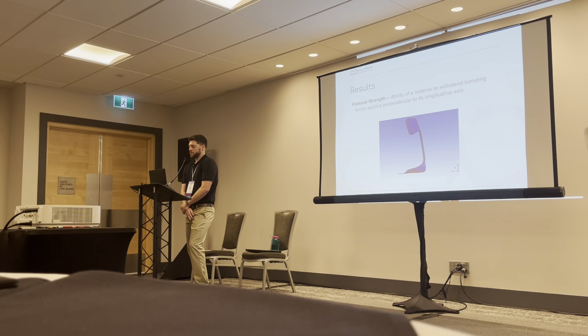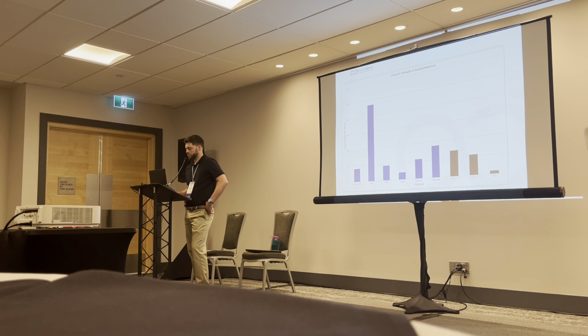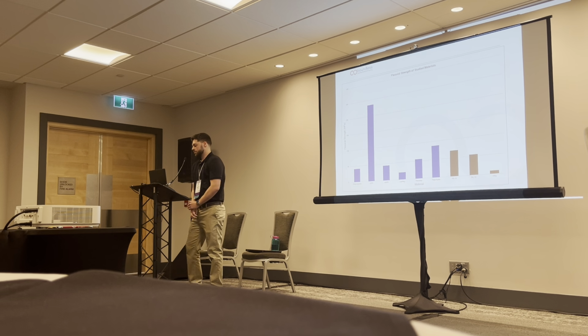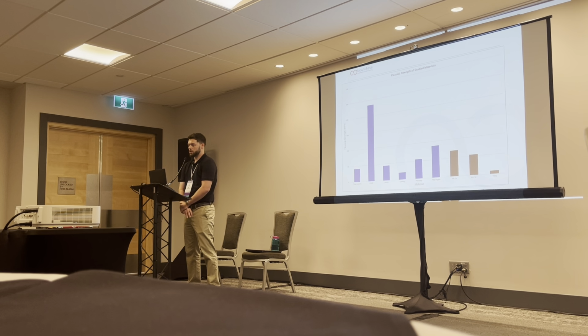The second property we looked at, flexural strength. So it's the ability of a material to withstand forces applied in a perpendicular direction. So the loading situation that we generally see in an AFO. So for flexural strength, we found PA11 and PA12 exhibit properties most closely to ProComp, and TPU again was a little bit of an outlier in this category, but was most closely related to the copoly and the traditional thermoplastic.